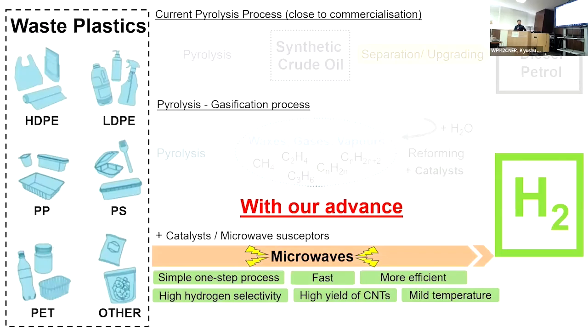Okay, once we find this catalyst, we do lots of comparison with how the current pyrolysis process can produce synthetic crude oil, and from distillation they could actually produce synthetic diesel and petrol. And for hydrogen applications, they always combine two processes, pyrolysis followed by a gasification process, to generate the hydrogen. So in our process, you can see how powerfully the microwave directly interacts with iron aluminum oxides. And at that active site, they could form a very simple, one-step, faster, more efficient stripping of the hydrogen. And especially we could achieve a very high selectivity to hydrogen and carbon nanotubes.